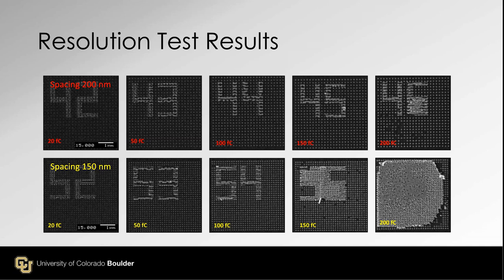On the top row, the spacing is fixed at 200 nanometers, and I'm just increasing the point dose from 20 to 200 femtocoulomb. On the bottom row, my spacing is 150 nanometers, and I use the same 20 to 200 femtocoulomb range. This is after pattern transfer. As you can see, 150 nanometer spacing with a 200 femtocoulomb exposure didn't work very well. It didn't do a good lift-off there.